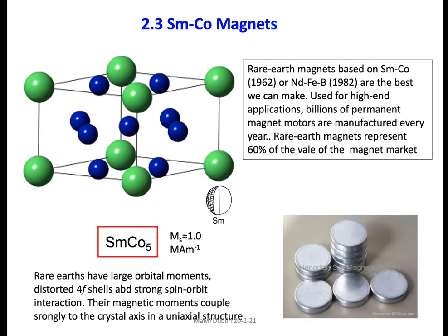You can see there's a little picture of samarium. It's a slightly elongated charge distribution, and that then couples to the crystal field, which is produced by the charge around the samarium. And in samarium cobalt 5, which is hexagonal, it's got an easy axis. Every hard magnet must have a uniaxial structure. There must be one axis that's much preferred for the magnetization to lie in. Otherwise, it turns out to be impossible to get coercivity. If it was cubic, you would never get any significant amount. But this is where, for the first time, quantum mechanics came in.